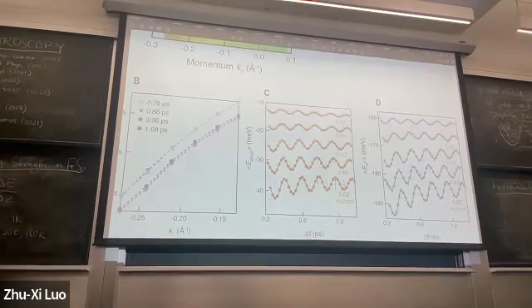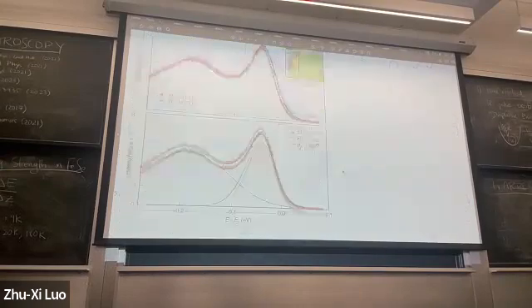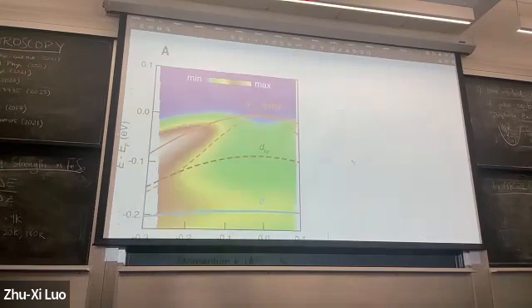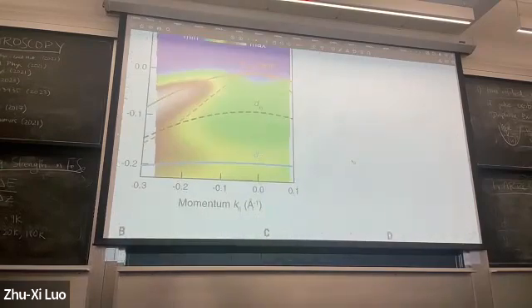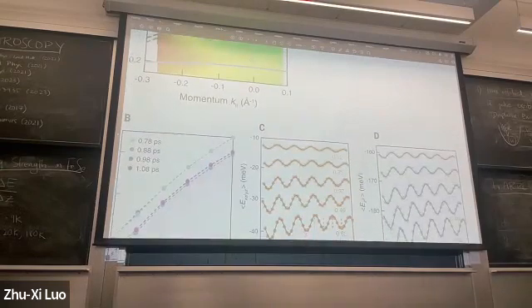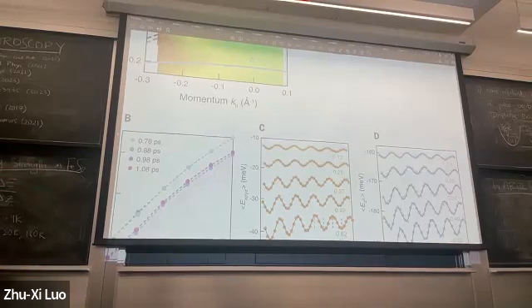So in the band structure near, on this range of momenta that they're able to, yeah, the punchline is that you can extract the frequency of this oscillation and see that it's the same as the frequency of the lattice oscillations. And then you can plug in the extracted amplitude for the oscillations of the band and the oscillations of the selenium atoms and extract this electron phonon coupling directly.